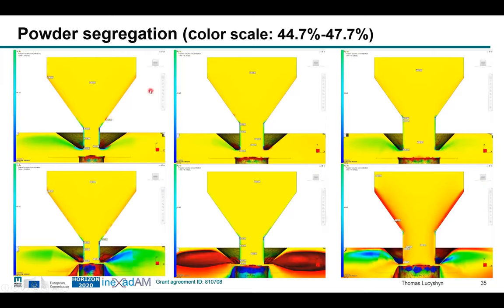And what is shown here in the results is the powder segregation. So basically it's the volume concentration of the powder. And you can see some differences between the different setups. So here, for example, you would see on these walls, there would be some higher concentration of powder due to the different flow conditions here.